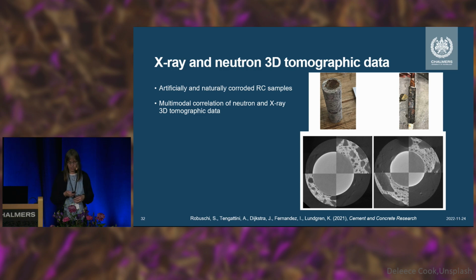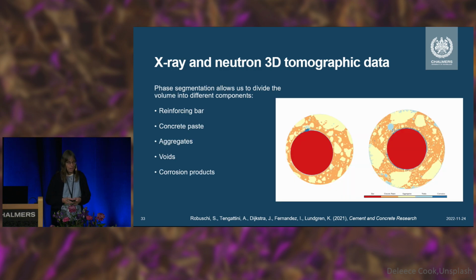So then we did, as I said, both neutron and X-ray tomography. And by using phase segmentation, we could actually divide the constituents, so to say. You see the different colors for the different parts. You could see the aggregates, you could see the cement paste in between, we could even see the corrosion. So the dark blue parts are the corrosion, and the red one is the steel.